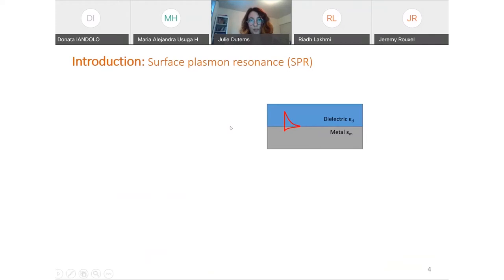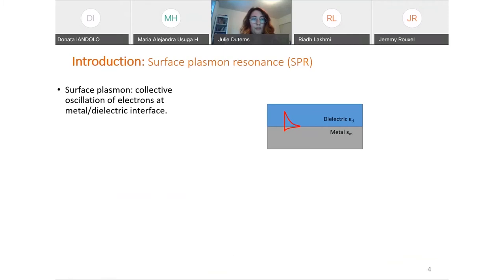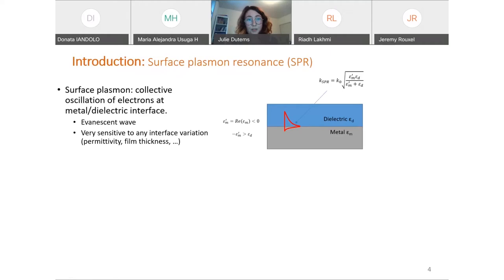What is a surface plasmon resonance? It is defined as the collective oscillation of electrons at the metal and dielectric interface. It can be seen as an evanescent wave that will propagate at the interface of the dielectric and the metal, and that will scan the interface. It is very sensitive to an interface variation, such as the permittivity and the film thickness. The propagation constant depends on the light wave vector, the real part of the permittivity of the metal, and the permittivity of the dielectric.